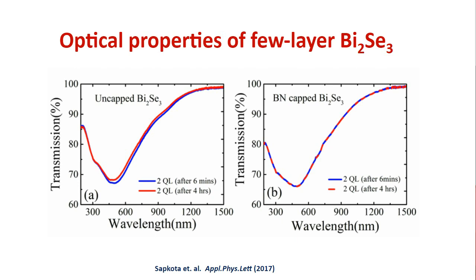Okay, so I'm looking at the transmission data of a 2 quintuple layer sample. Unlike MoS2, we had better luck depositing a 2 quintuple layer bismuth selenide. So this is about 2 nanometers. I'm showing you a couple of data sets here. For the sample on the left, we left the bismuth selenide uncapped, meaning there was no protective layer on it. On the right, we protected the layer with a thin boron nitride insulator. Boron nitride is a wide band gap insulator, so it's transparent to the light, and we were not worrying about its absorption.